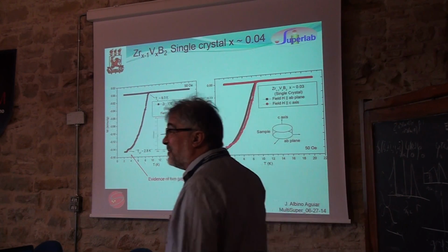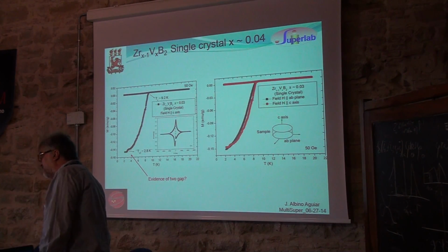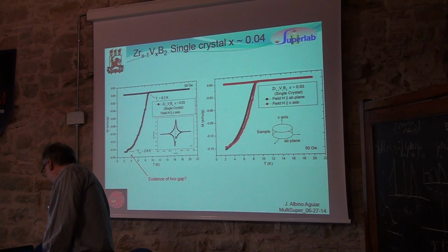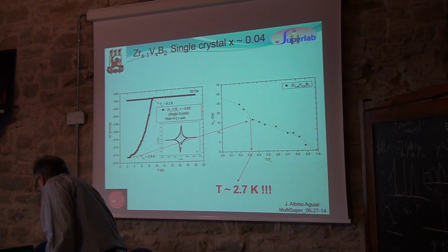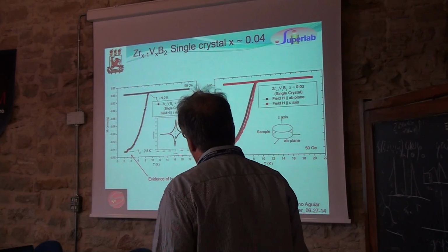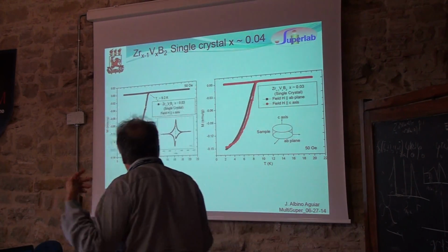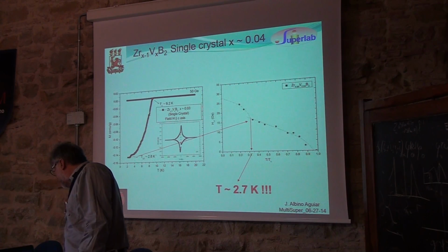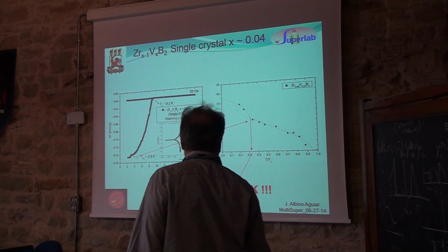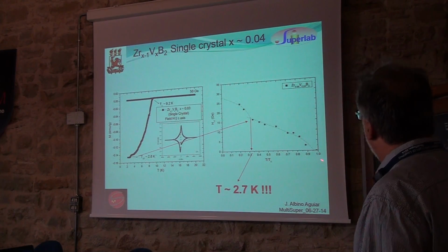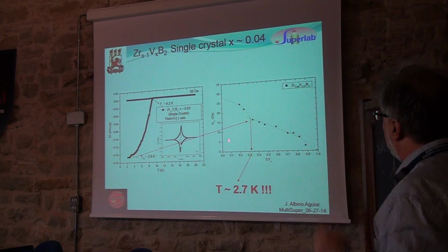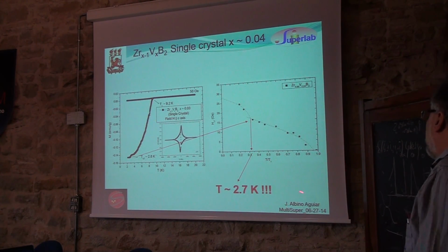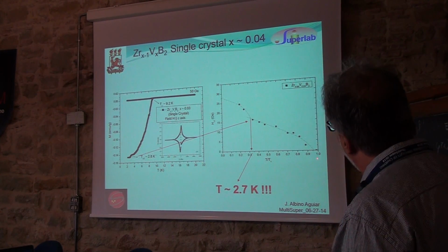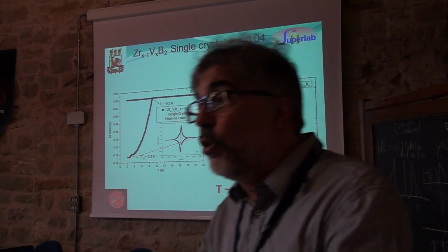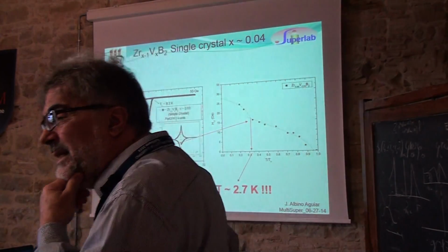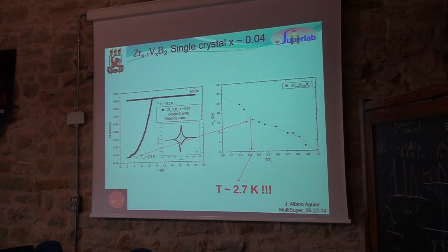Is this evidence of two gaps? We don't know, but if we agree that it is evidence for two gaps, then you can do this. You can draw the first critical field, its temperature dependence. If you draw a contribution from the pi band and the sigma band like this, you would fit the data. Of course, we need to measure the gap in this material.